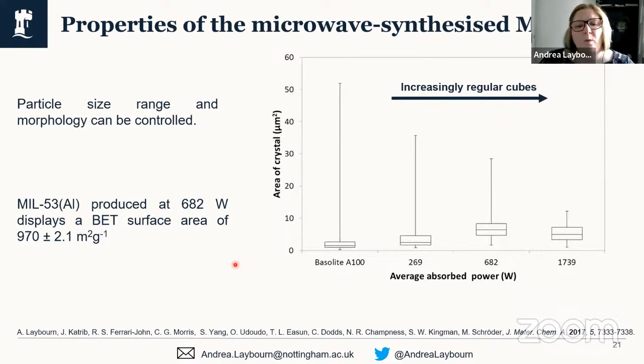So when we were increasing the average absorbed power, we saw differences in the morphology of the particles and the particle size range. So what I've got here on this graph is we've taken the area of a face of the crystal and we've plotted this against average absorbed power, where the Basolite A100 material is the commercially available material which is not synthesized by microwave heating, but this was our benchmark. You can see that the area of the crystal on this box and whisker plot, the particle size distribution was very, very wide. When we look at the microwave prepared materials and increasing power, we go from wider particle size distributions to narrower particle size distributions.